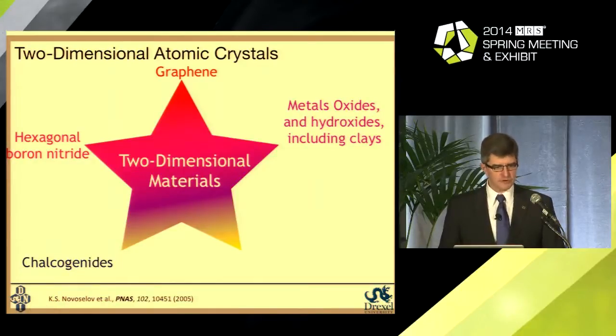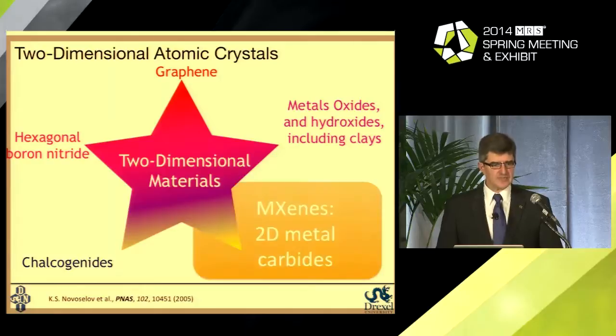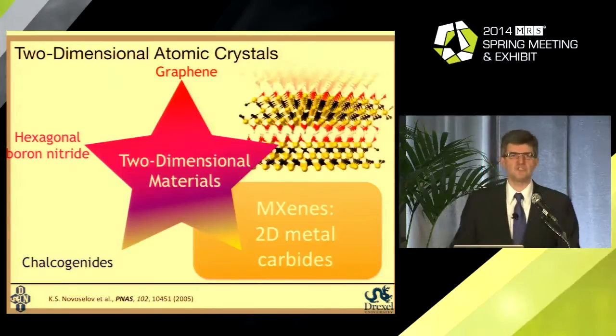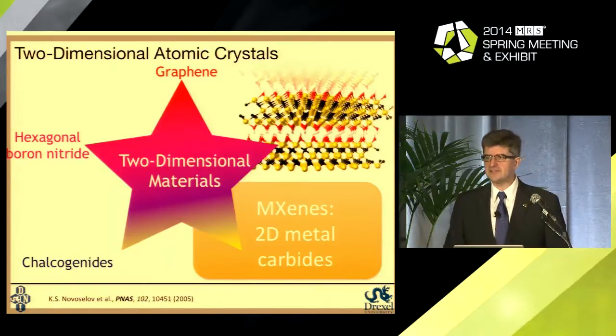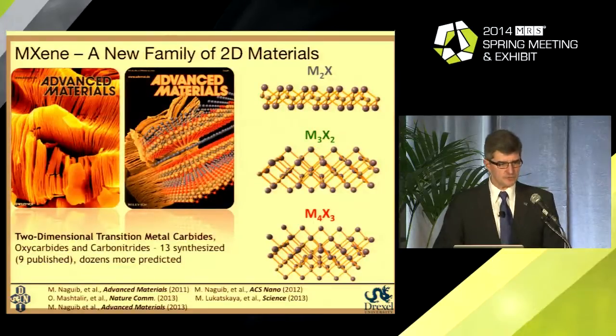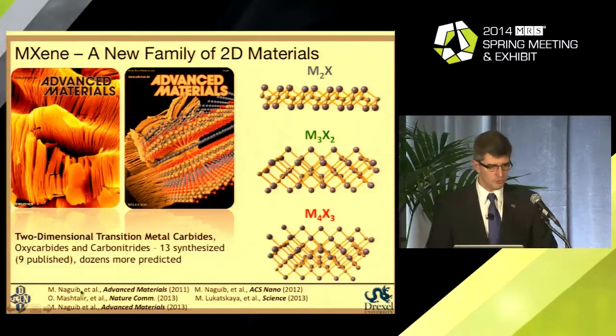However, so far there have not been any transition metal carbides made in a two-dimensional state, until we discovered about 3 years ago an entirely new family of two-dimensional materials based on metal carbides. We call these materials MXenes because they're built of M and X atoms. And what you see here is the cover of the journal. This is the first publication on MXene, which appeared in 2011.